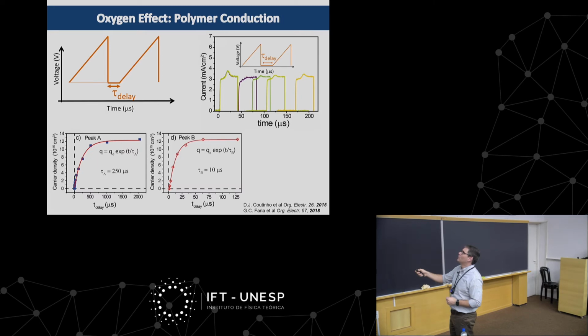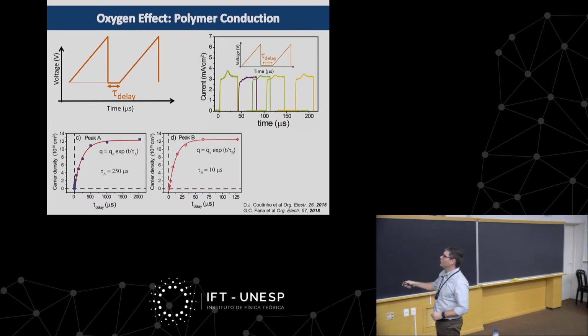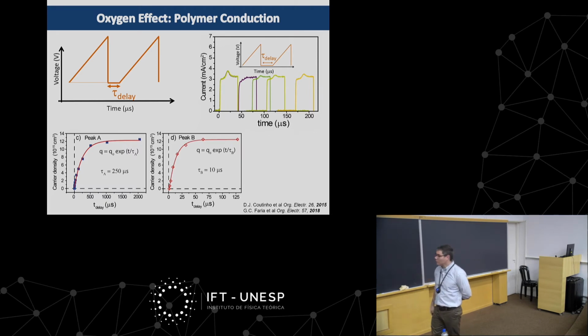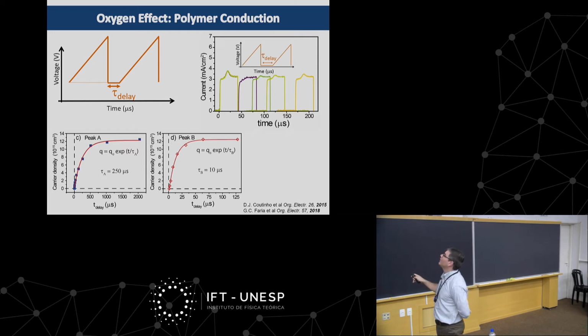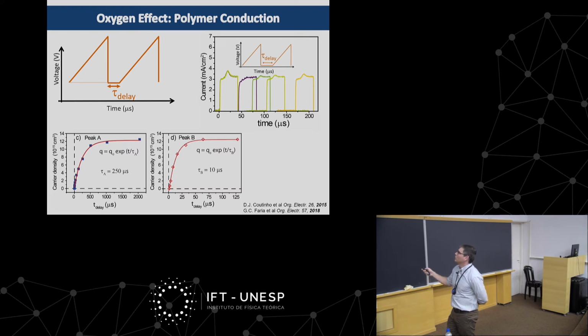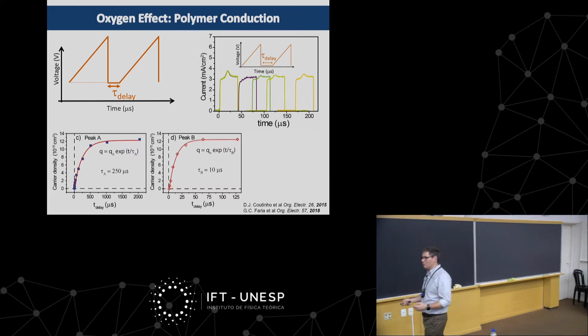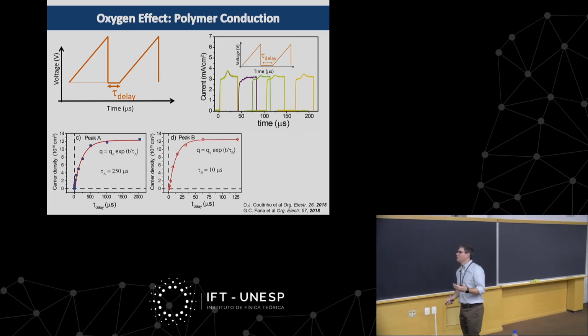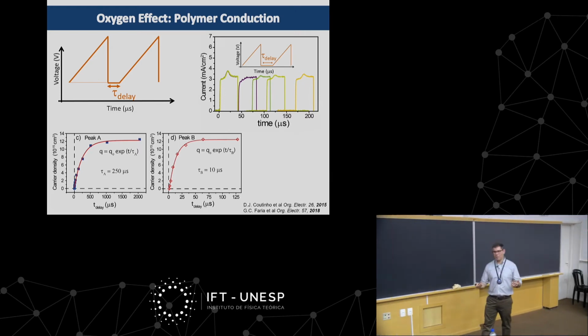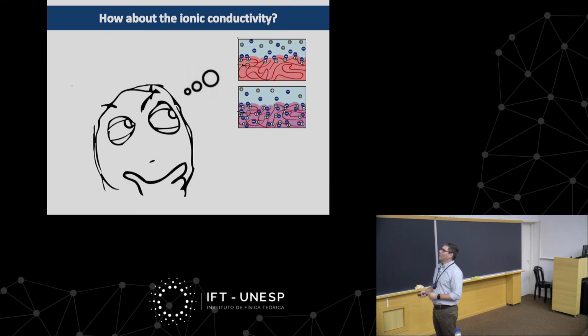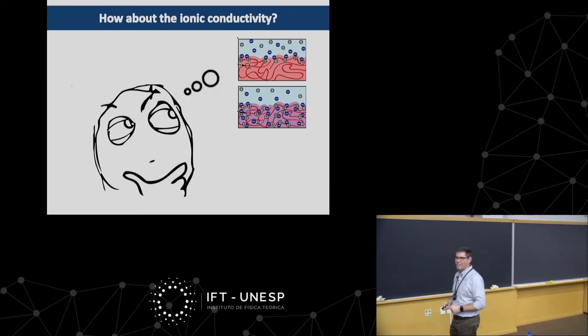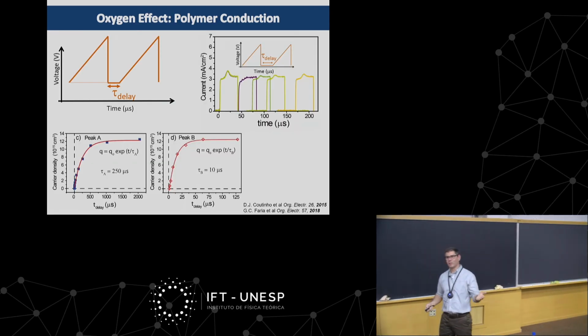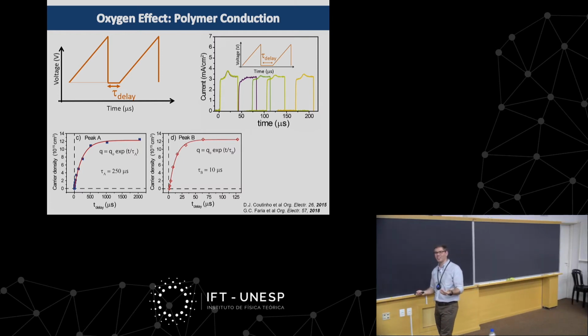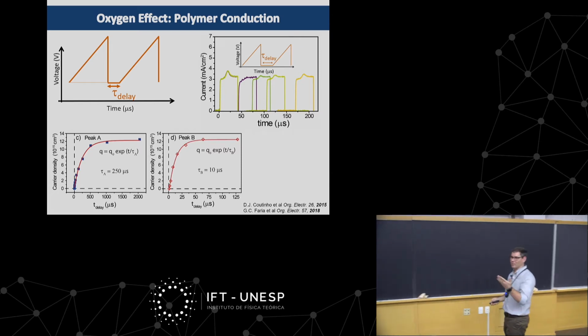We could play with the distance between two subsequent linearly increasing voltages to capture the recovery kinetics of those reservoirs. We did a lot of calculation as well on this matter. I don't want to go into details because I want to move to the next topic. But those generated two very nice papers that gave a good contribution to a field of organic electronics that wasn't so explored because of a lack of methods to access and study those charges. Okay, so I think using not only my small LED that I passed around but also this oxygen doping work, I have proved to you that yes, polymers are capable of conducting electronic charges, either electrons or holes. You can see that happening in front of your eyes.